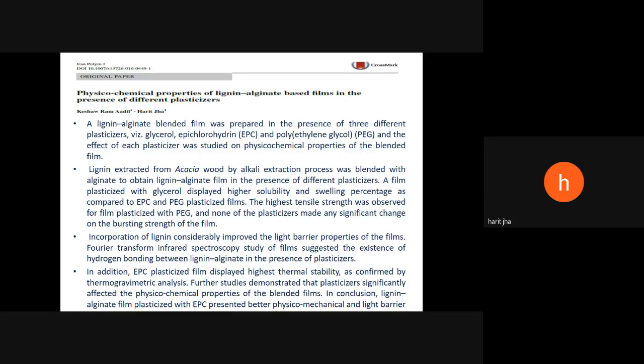Now, in this part, I'll be discussing one application through the paper which we have published. For example, this paper was published in Iranian Polymer Journal, it's a very old journal. In this, we have discussed the physicochemical properties of lignin alginate film in the presence of different plasticizers. In this work, a lignin alginate blended film was prepared in presence of three different plasticizers: glycerol, epichlorohydrin, and polyethylene glycol. And the effect of each plasticizer was studied on physical properties of the blended film. Lignin extracted from acacia. Now, why did we choose acacia?